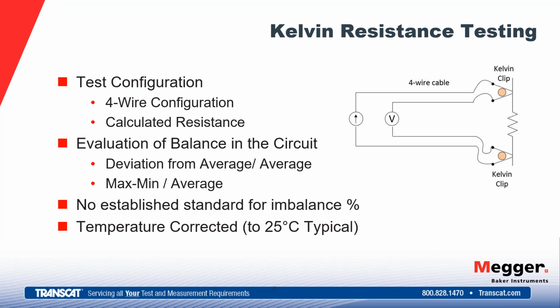We're also going to take our temperature, and the resistance that we measure, we're going to temperature correct it, because as temperature increases, so does the copper resistance. So if we want to trend over time, then we're going to need to temperature correct. Typically that's at 25 degrees C. I have seen some places that will actually use 20 degrees C for that correction factor, or the temperature that we're correcting to. And it doesn't matter whether it's 20 or 25, you want to be consistent in that measurement so you can trend over time to see how that trend is going as you progress through the testing.